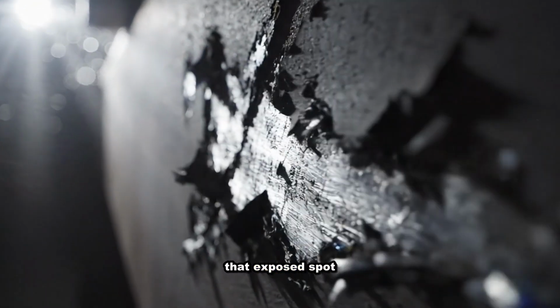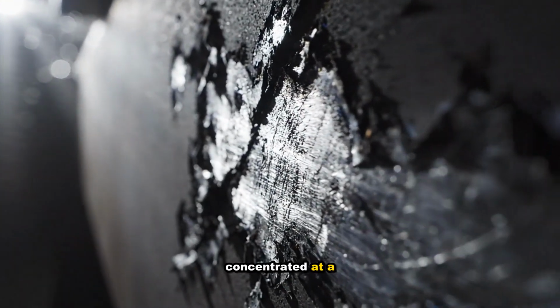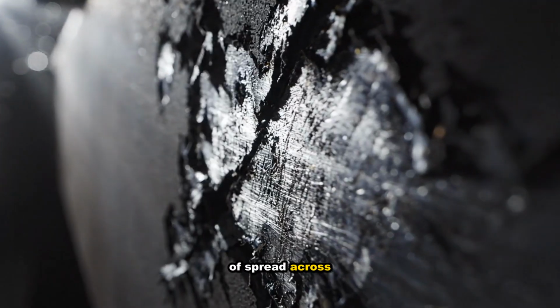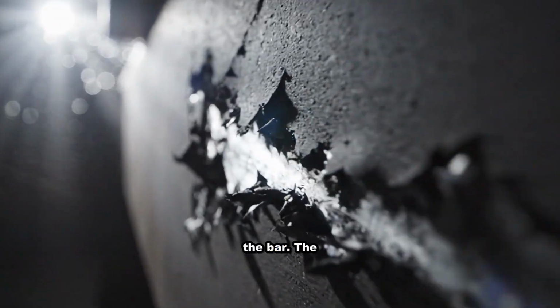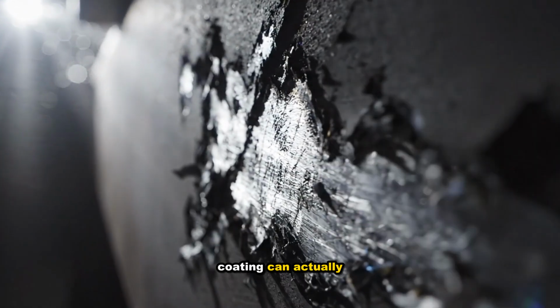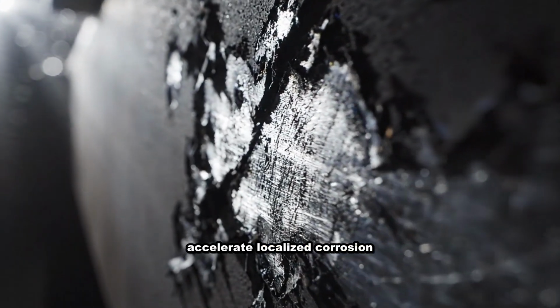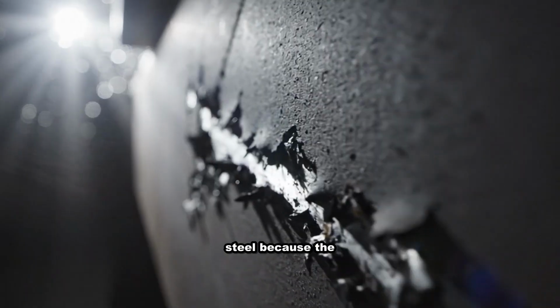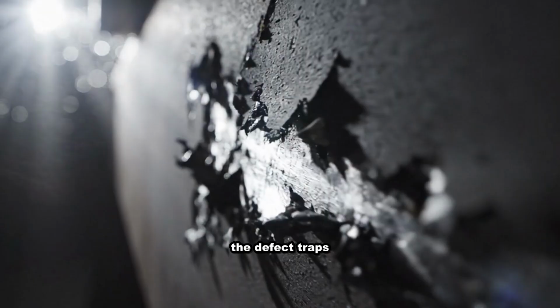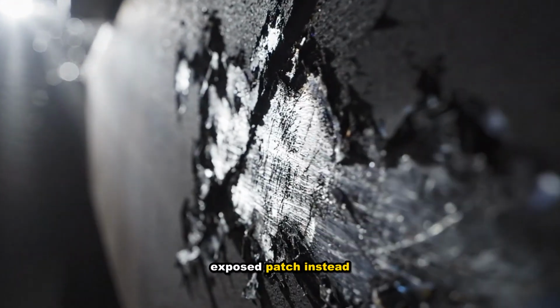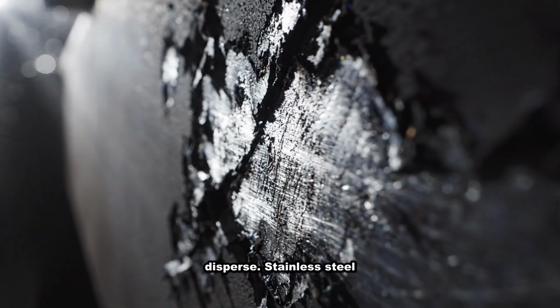And now that exposed spot corrodes in isolation, concentrated at a single location instead of spread across the bar. The interesting part is that damaged epoxy coating can actually accelerate localized corrosion compared to bare steel, because the intact coating around the defect traps moisture and chloride against that one exposed patch instead of letting it disperse.